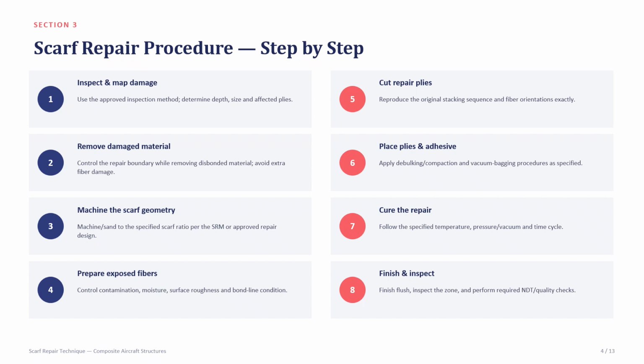And fourth, we have to prepare the exposed fiber and control contamination, moisture, surface roughness and bond line condition. And fifth one is cut repair plies to reproduce the original stacking sequence and fiber orientation exactly. And sixth one is place the plies and adhesives. Apply debulking or compaction and vacuum bagging procedures as specified. And cure the repair. Follow the specified temperature, pressure or vacuum and time cycle. And eighth one is finish and inspect. Finish flush, inspect the zone and perform required NDT or quality checks.